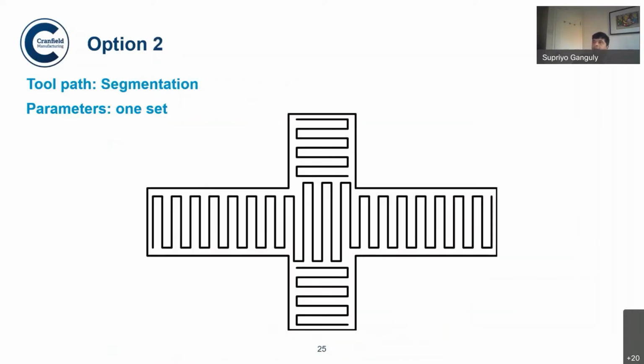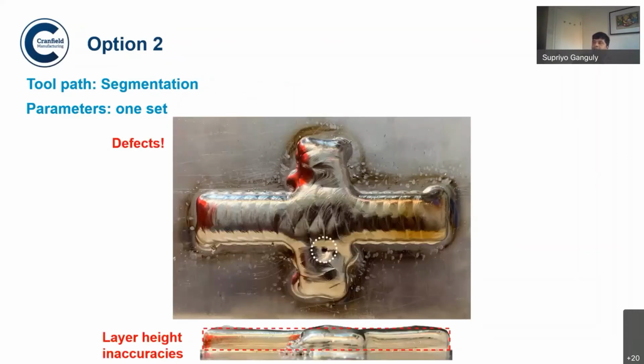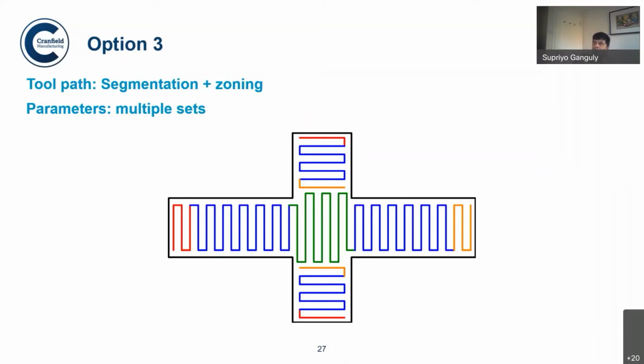So now there were some segmentations done where the deposit parameters remain the same, but the tool path was changed. And here also, as you can see, there are some inaccuracies and some defects, although it reduced to some extent. Now this is the other part, the final part building, which was done here, where we managed to rectify all these defects and the resulting defects.